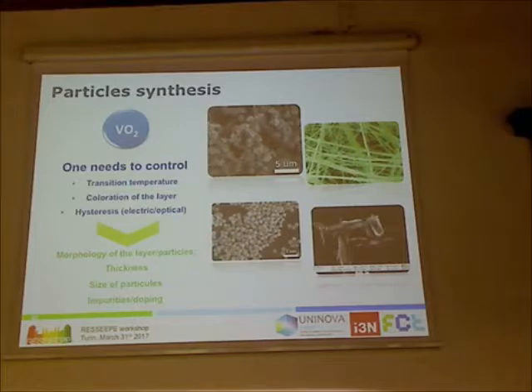The coloration of the layer is grayish, as I told you, so you cannot do much about that. This hysteresis is important - it's the window that you have in a heating and cooling cycle. Imagine that it will change phase at 68 in heating, but when cooling down it will change at a different temperature, for instance 10 degrees different. This can create some issues.